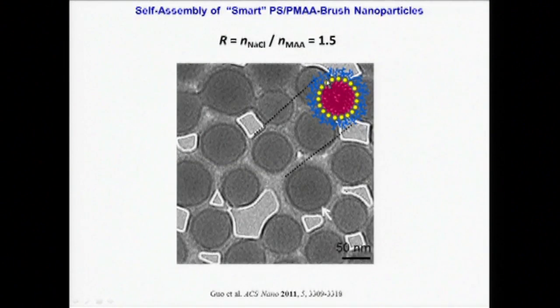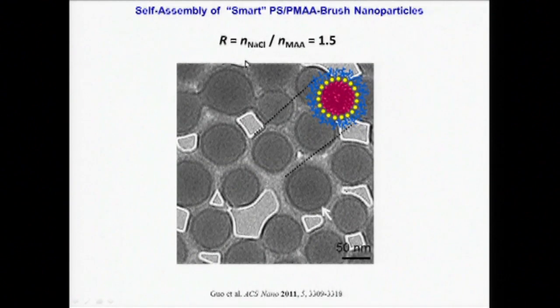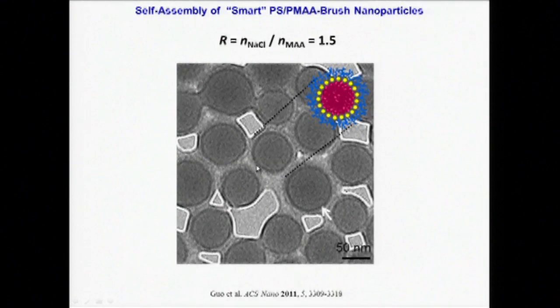In fact, if we add a controlled amount of sodium chloride to the nanoparticle dispersions before self-assembly, and then add water and dialyze, with all other conditions being identical to the formation of worms, we get a very different type of colloidal assembly, this one reminiscent of spherical block copolymer micelles, but with quantum dots localized at the polymer-polymer interface, as shown in the schematic.